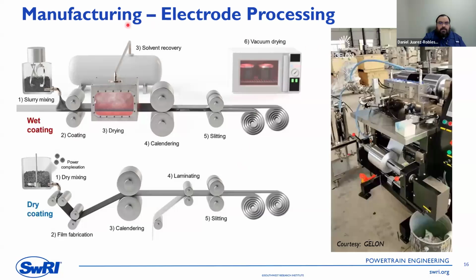Now, just to give you an idea how the processing looks when you go from the small scale to the large scale, you will see that the process is the same. You mix the slurry, you will have this wet slurry here, then you will cast it, set the desired initial thickness. When you dry it, just because you are removing the solvent, the electrode will compact.